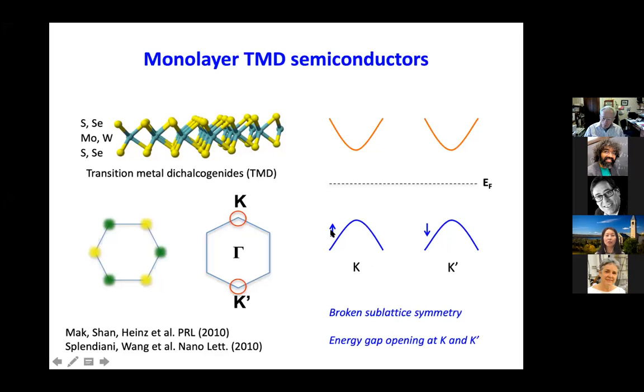But in general, this material has time reversal symmetry. So if you go from the K point to the K prime or minus K point, spin will also flip. So overall, the band structure looks like this. And it's a semiconductor, so the gap is on the order of 1 to 2 eV. And that's very optics friendly, something that we can probe with photons.